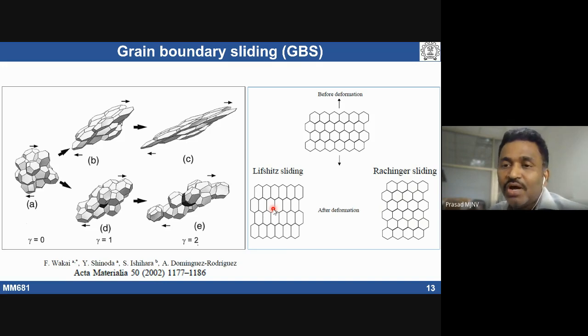When you go to high temperatures and you have a particular grain size, we may see dislocation creep and also diffusion creep. Apart from grain boundary sliding, we may see either diffusion creep or dislocation creep. If diffusion creep accommodates your grain boundary sliding, that is called Lifshitz sliding. If the dislocation mechanism is accommodating grain boundary sliding, that is called Rachinger sliding.